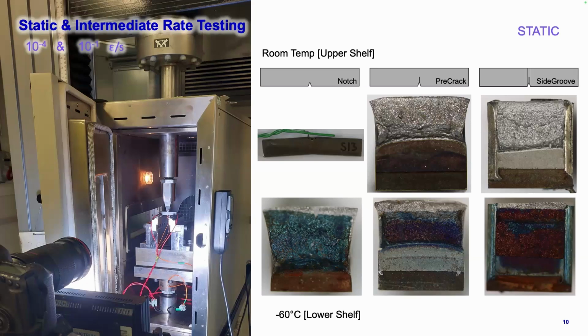Final areas from this: where can we go forward? One area that I'm continuing to go through is to extend this not just for Charpy, but for the same size samples with the same difference in constraint, but for different rates. I can now show that there is a valid range where I can observe good fracture information and extract valid data. Is that range good within slower tests? Will a static test be better for dynamic validity? Will the validity start to work in those areas? So I have static and intermediate mid-range, as fast as my static system will go. I don't have full data to show for that.